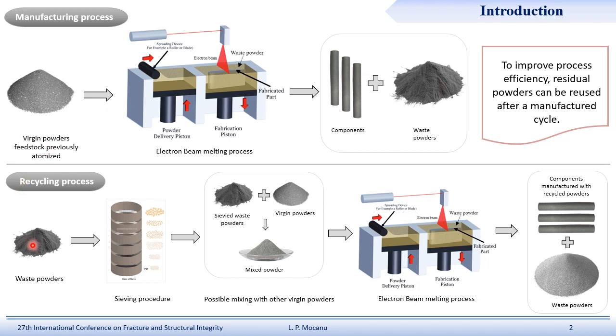So, starting with this waste powder, it is firstly sieved in order to eliminate any damaged particles, broken particles, and so on. And then it is also possible to mix this sieved powder with other virgin powder in order to lower the oxygen content. And then, starting with this mixed powder, another layer-by-layer manufacturing cycle will begin, at the end of which we will obtain other components, this time made with recycled powder, and other waste powder.